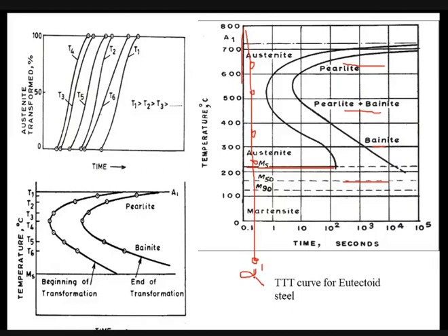During this austenite to martensitic transformation, when you heat this 0.8% carbon steel sample at more than 800 and quench it into water, obviously you require water or brine solution in order to quench it in less than 1 second. Due to rapid cooling, the hardness of the sample increases. You can see some surface distortion over the sample. After the quenching process, steel becomes very hard. That steel you cannot use as it is in applications, because if you measure its hardness in Rockwell C scale, it goes to more than 50 HRC. Such high hardness samples we generally do not require in the mechanical field. So we need to control the hardness of the steel sample.